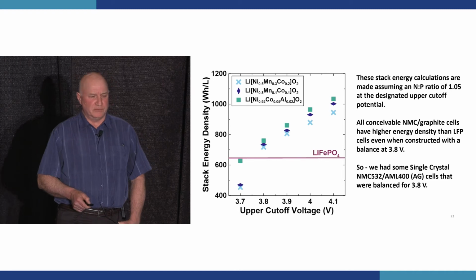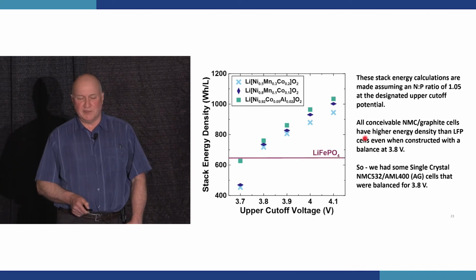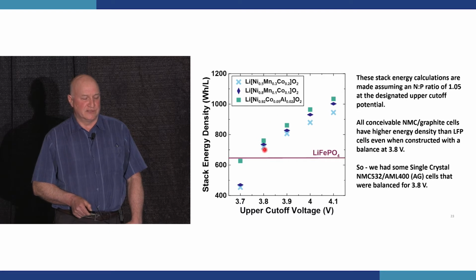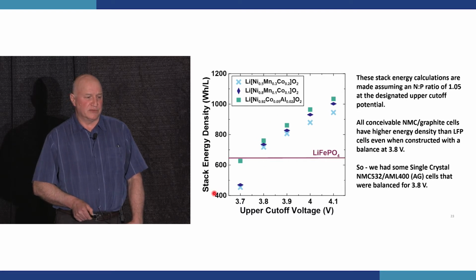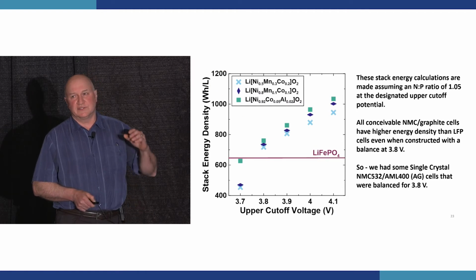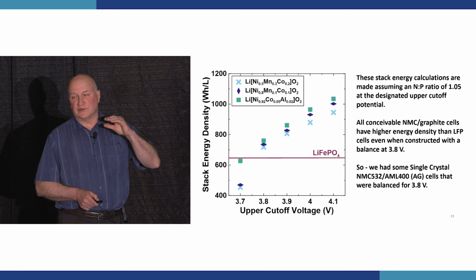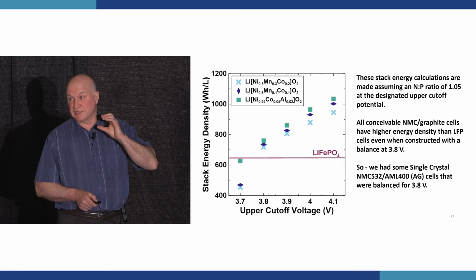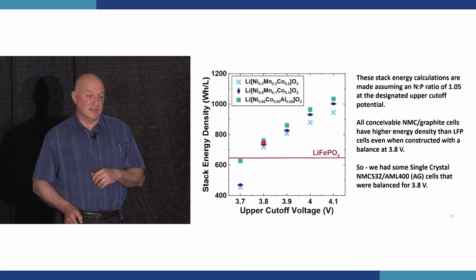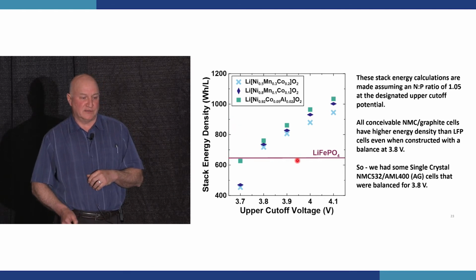Yeah, so before we do that, let's talk about whether it's sensible to make these NMC cells that are balanced for low operating voltages. So here I show the stack energy density in watt-hours per liter. This is the energy density of the graphite, separator, positive electrode, separator, electrolyte stack in a cell. And LFP is shown here by the horizontal line. Its stack energy density doesn't depend on the voltage above 3.5 volts because that's fully charged. So about 650. And NMC, any of these NMCs or NCA materials made into a cell balanced for 3.8 volts has a higher energy density than LFP.